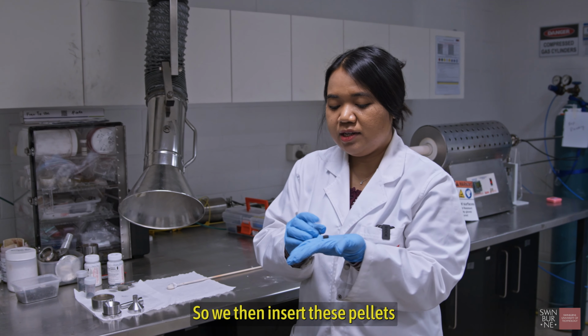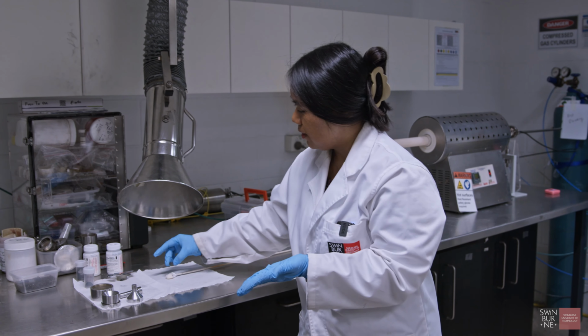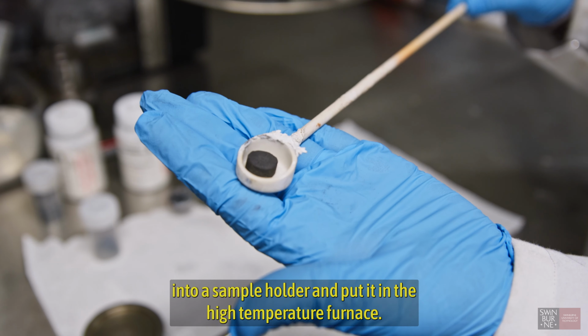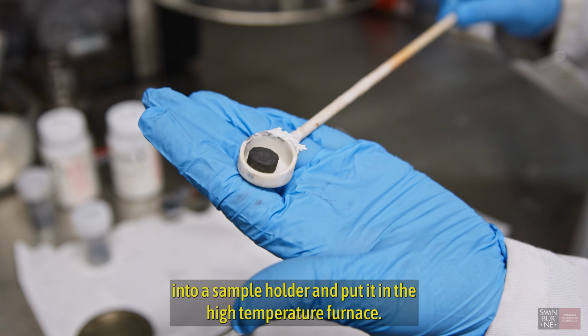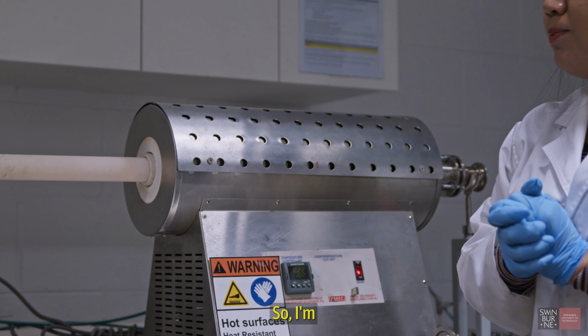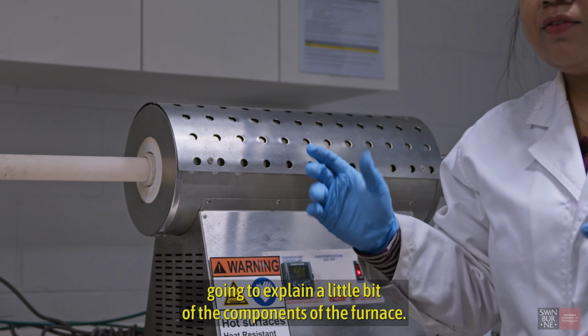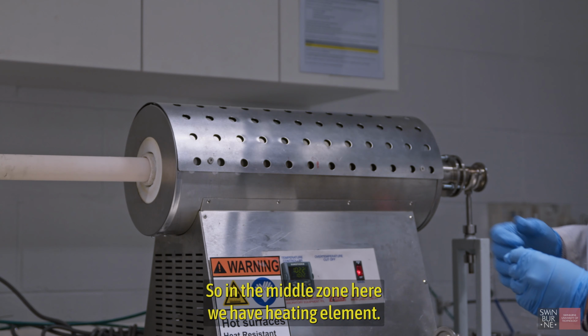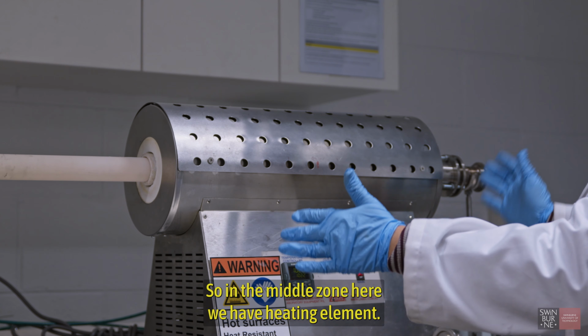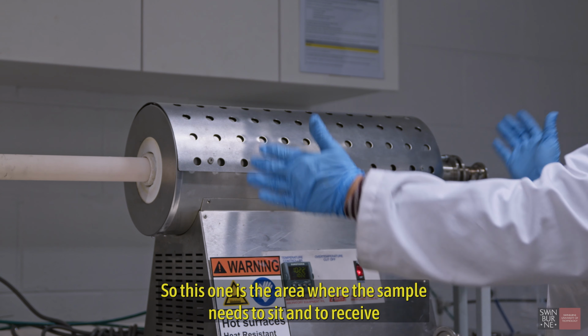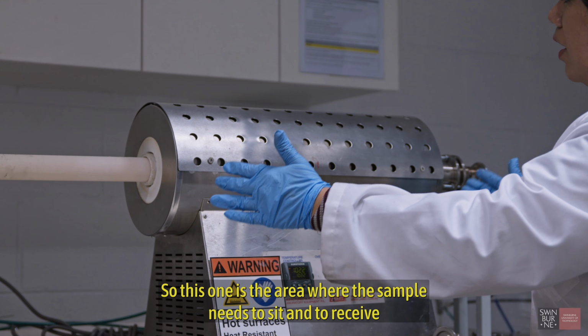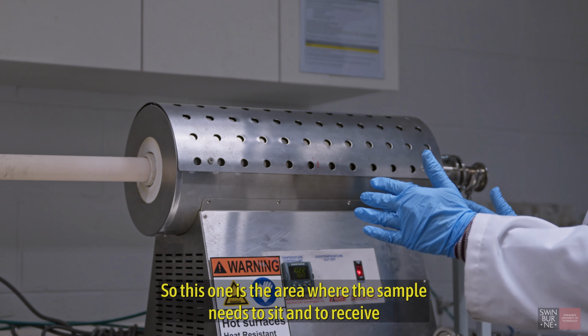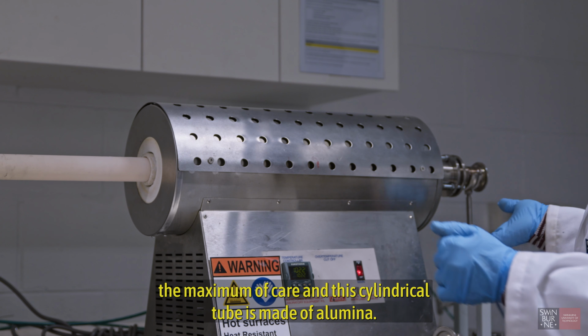So we then insert these pellets into a sample holder and put it in the high temperature furnace. I'm going to explain a little bit of the components of the furnace. In the middle zone here, we have heating elements. This zone is the area where the sample needs to sit and to receive the maximum of heat.